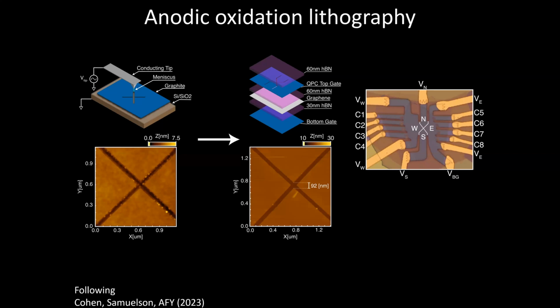And the miracle is that if you then try to pick up this cut up piece of graphite with a boron nitride, you pick up only the parts that you wanted, and you don't pick up any of this residual amorphous carbon. So you can now pattern gates with 10, 20, 50 nanometer resolution in whatever shape you want, and then you can integrate them into your heterostructure as you pattern them.